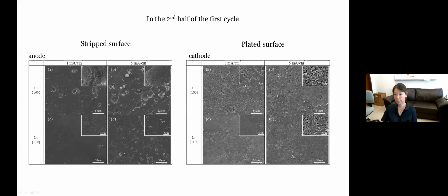Now, in the second half of the first cycle, the anode side that was plated now gets stripped, and the cathode side that was stripped now gets plated. Now we see very consistent results. The pitting process that occurs at low current densities occurs only on lithium 100, but not on the 110. But at high current densities, both happen, but the density of the pits is much higher. And there's a slight difference in the cathode side that is plated. Now, at this point, you'd say the plating of the two is not much different, which is true.